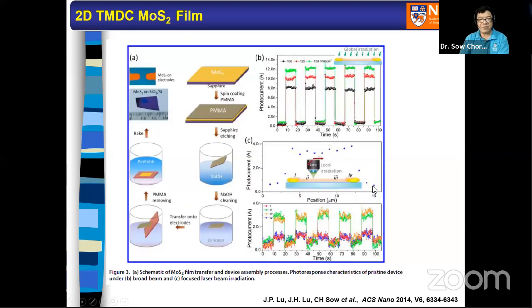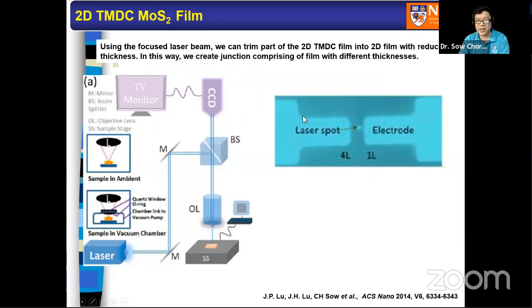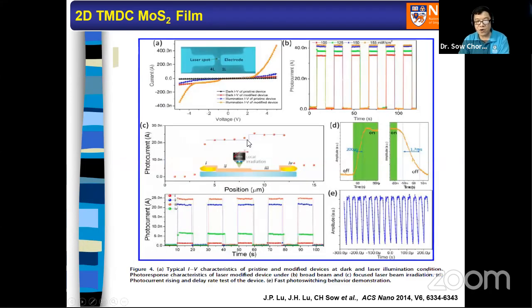And now I want to show you this picture. Here is a picture of two electrodes. In the middle, you can't see clearly, it's actually MoS2. And Jinpeng used laser beam to modify the MoS2 on the right-hand side to trim it down from four layers to one layer. And lo and behold, the junction achieves very strong photocurrent because you are tuning a junction with different band gap materials. They are all MoS2, but because of different thickness, it has a different band gap. But the details are more involved. Not only are they different thickness, in the experiment we do everything in ambient conditions, so it will actually tune the oxidation process of this particular modification.